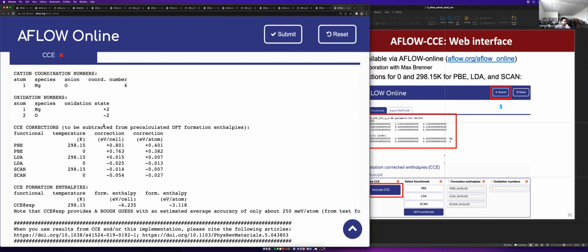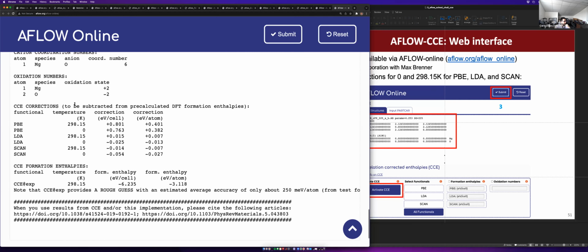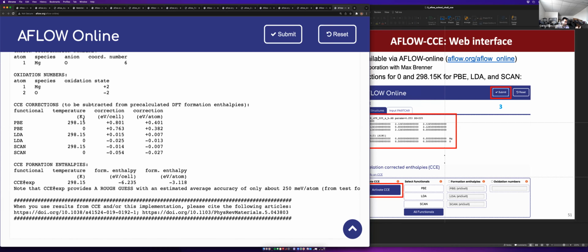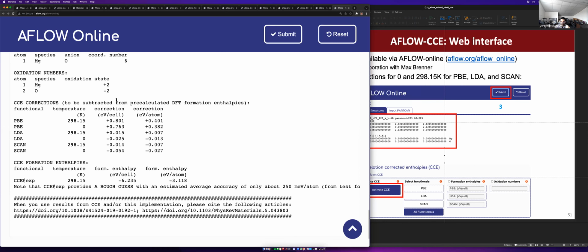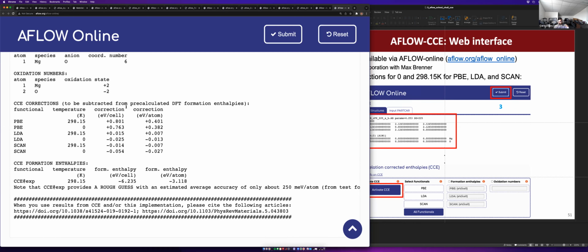Okay, so we know that magnesium is going to be a +2 oxidation state, oxygen is going to be -2, so that we have a neutral system. And then we can get the corrections. We can get corrections at room temperature, and then at 0 temperature, where we subtract off the thermal contributions. We can get the correction based on eV per cell, okay, and then eV per atom. Okay, so these are just different ways that we've normalized the corrections, but they're basically the same correction. And then we can also get the CCE, a rough estimate of what the formation enthalpy is, just based on the experimental values that we do the corrections for CCE. Okay, so we can get a formation enthalpy and then formation enthalpy per atom.